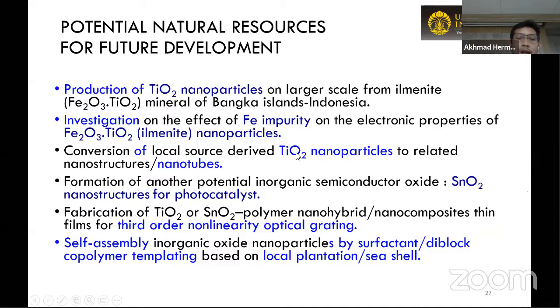And also, previously, in order to purify the TiO2 from the ilmenite, of course, the iron element is considered an impurity. That's why we are trying to improve the purity of TiO2 by removing the iron element. But in fact, the iron element in the TiO2 can be considered an element that can modify the band gap energy of the material.